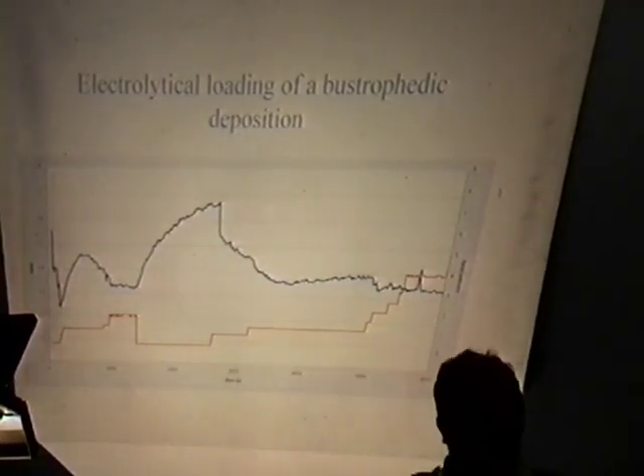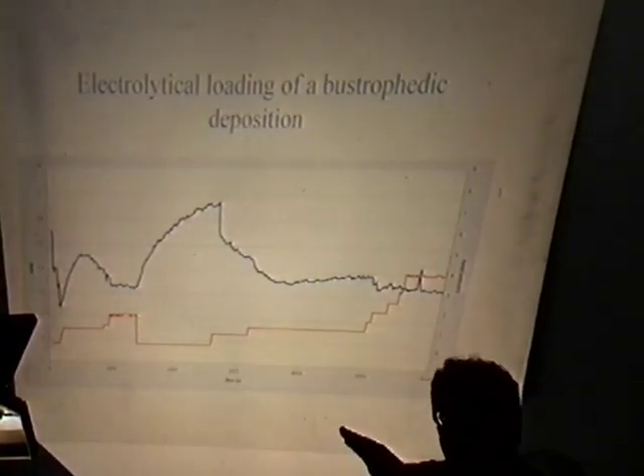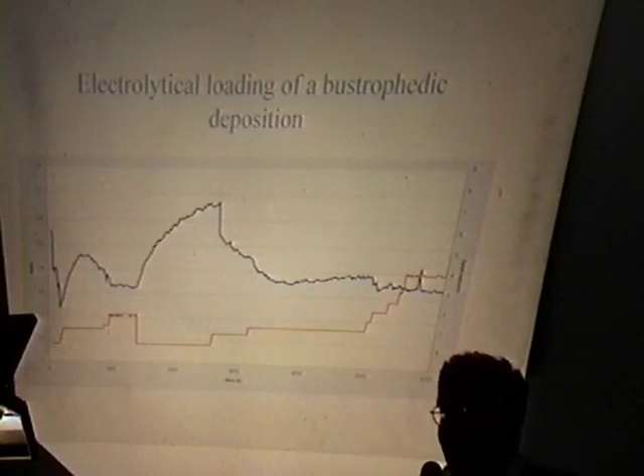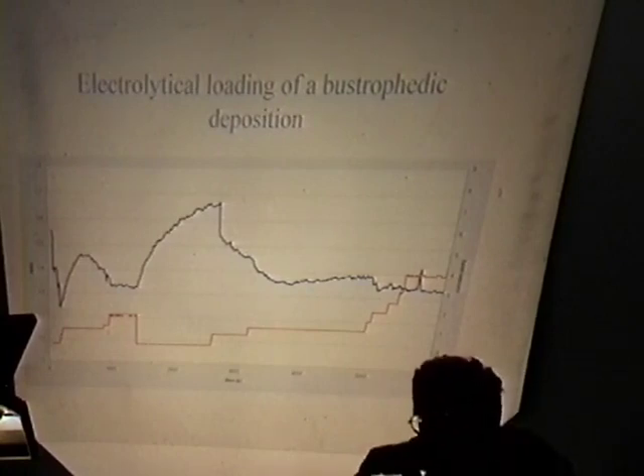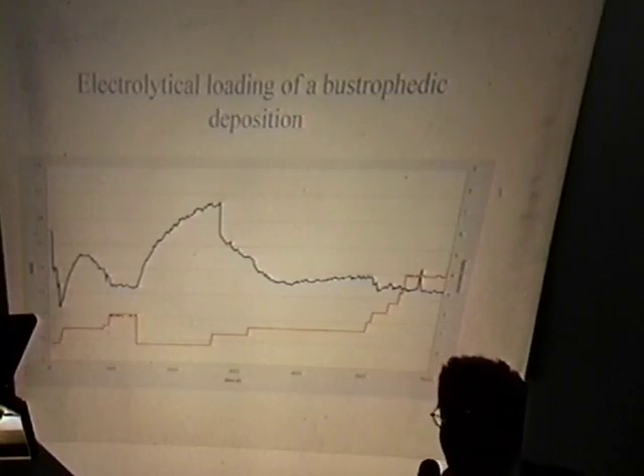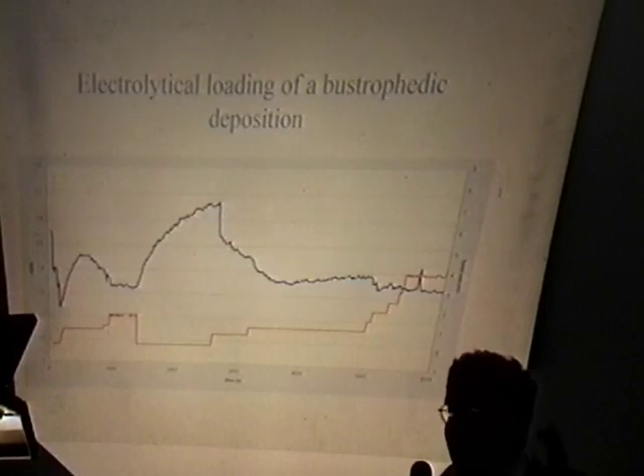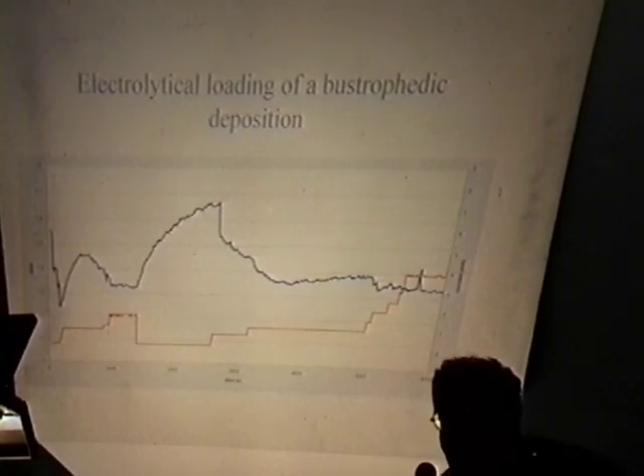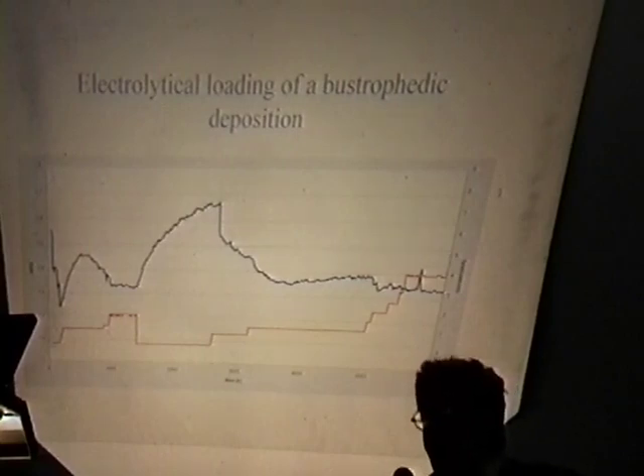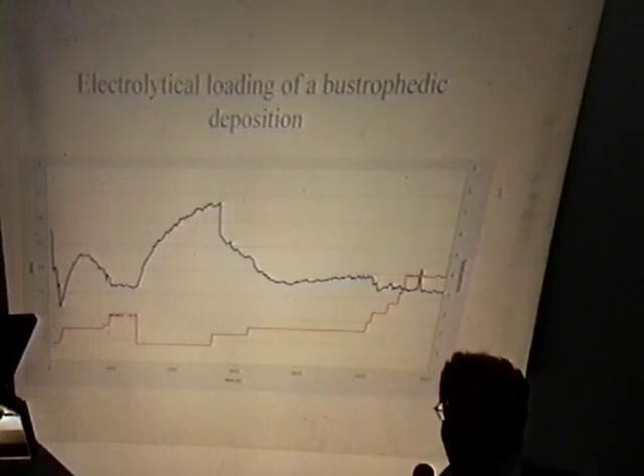That now we are on the right side of the Baranowski curve, namely in the descending branch of the curve. Namely, with the same regime, we have increased the loading, because in the first case the system settled in a situation where X was in the beta phase, and in the second case the system has settled at a much higher value of X.